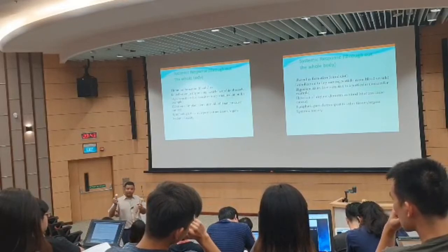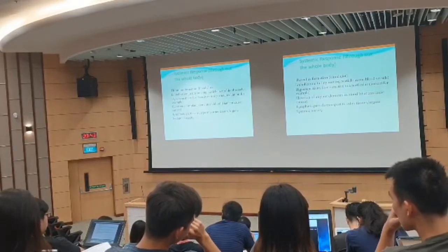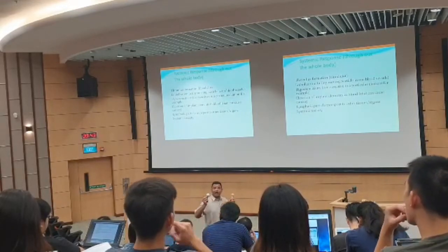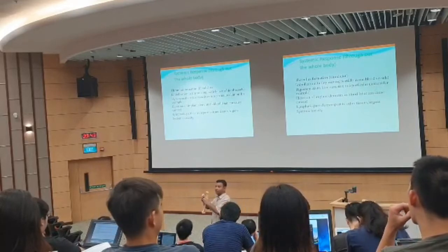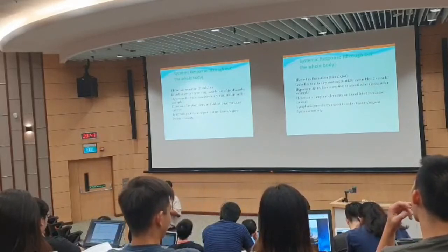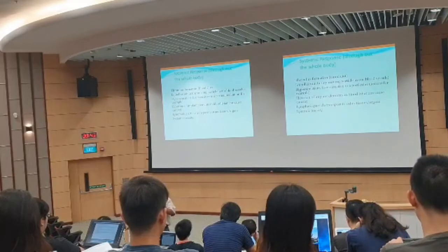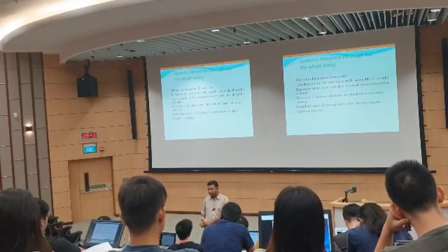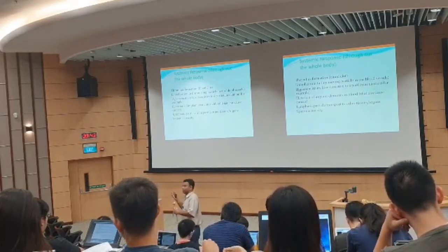Then, elevation of implant elements in the blood. As I mentioned, if this is a cobalt chrome alloy, it has been shown that the cobalt or chromium ions released from this material are present at an organ which is very far away from where it's implanted. So if we implant it here, we find the cobalt and chromium elements in the urine, for example, or in the liver.